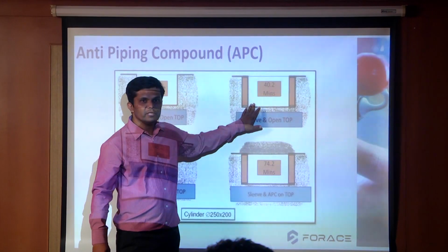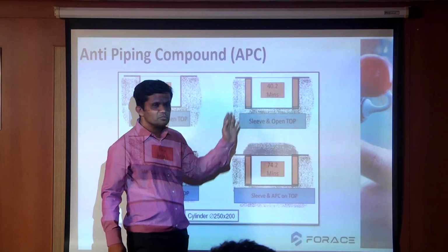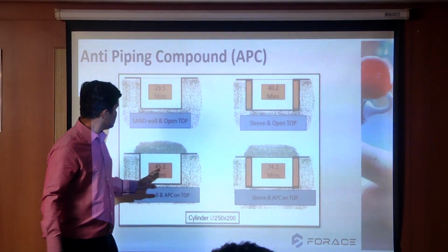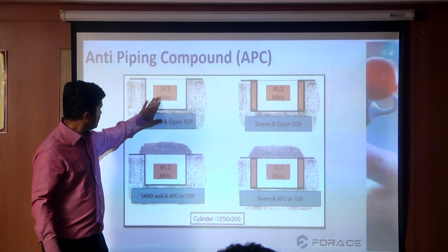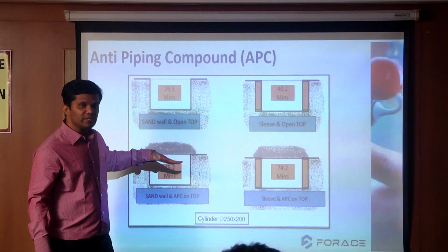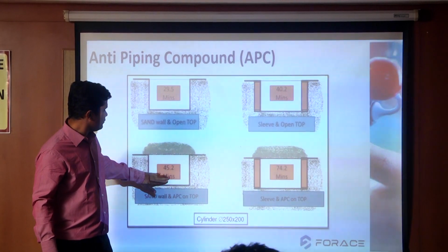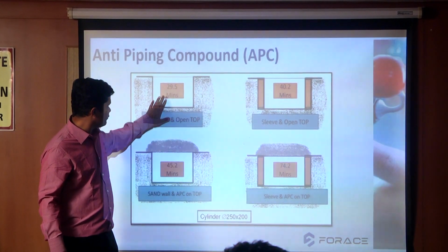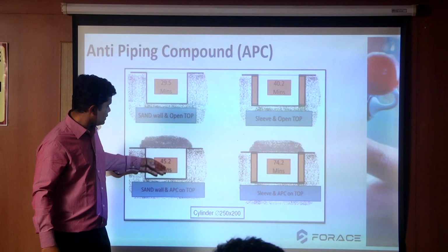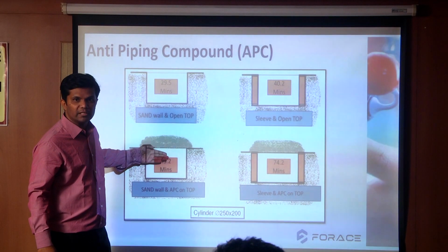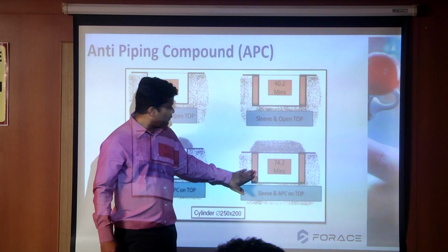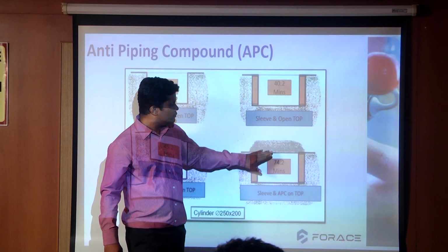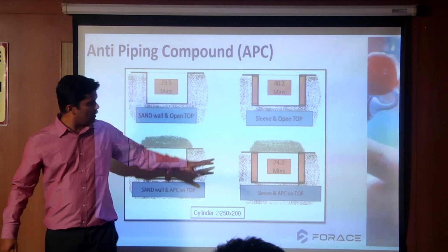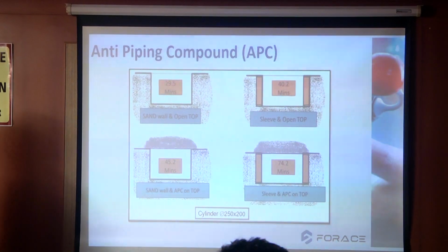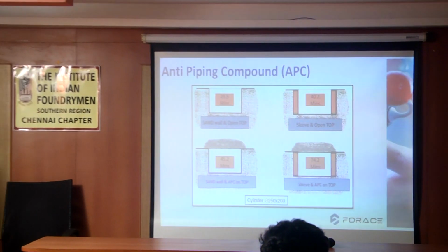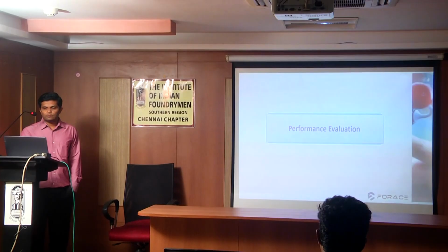If you put an open sleeve, then the solidification time is increased. Again, if you apply APC on the sand riser itself, and compare it with the regular one, the maximum heat loss will be restricted. And if you apply an open sleeve with APC, then again you can increase the solidification time.